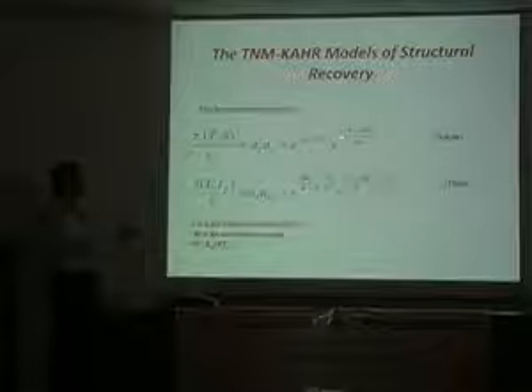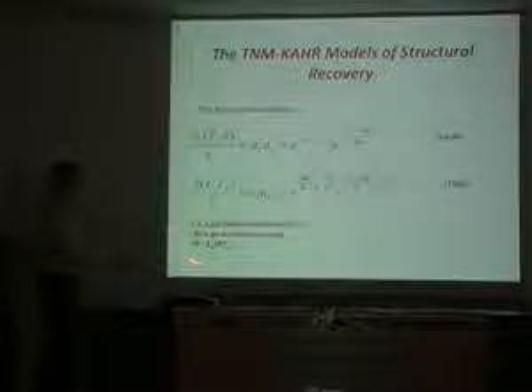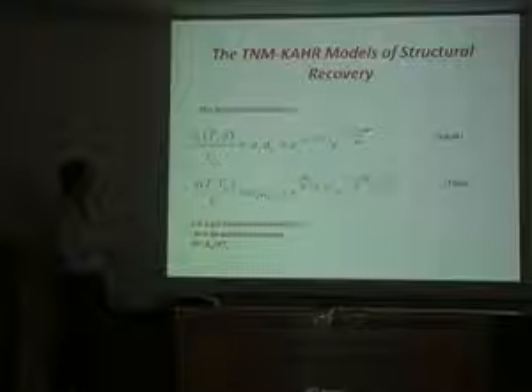And then Kovacs had it equal to e to the minus theta, T minus T reference, and then e to the minus (1 minus x) times theta delta over delta alpha, where theta has the role of something like an activation energy, but it's really related. Down here I say he has an EA as R T_g squared. Okay? And the x is called the nonlinearity parameter, and that's related to how you partition the response between delta and just temperature. Okay, so that's how Kovacs did it.